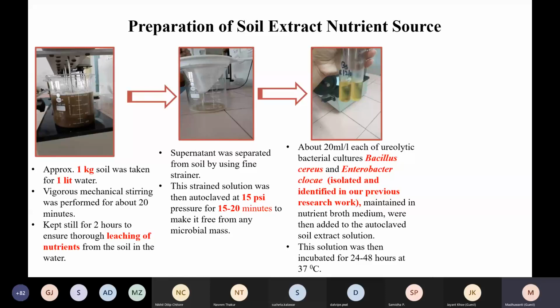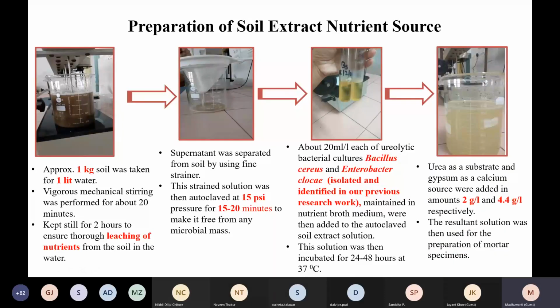Now the next step: this solution was taken in a conical flask to keep in the incubator. These are the two cultures which we had added. After incubating, we checked the optical density of this bacterial suspension in a spectrophotometer at 600 nm. The optical density of any bacterial suspension at 600 nm tells us about the growth of bacteria, and if it is above 0.6, it indicates that the bacteria have grown well. We got optical density readings of about 0.8 to 0.9, which indicated that the bacteria were profusely growing using this soil extract as the sole nutrient source.